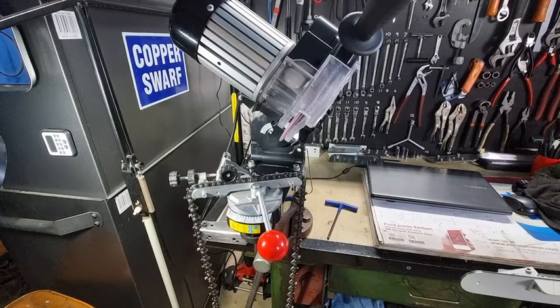If it's very, very light blue and it's only a small amount, you're not going to do damage to the teeth. But if that tooth is very, very blue, there's a good chance that you could damage the leading edge, which is a top plate cutting angle. And that's where you could get some damage because you excessively use the grinder. And that would be detrimental to the hardening of the tooth, and you'll increase the brittleness. You cause all sorts of damage. And that's what you want to avoid. So that's all this video is about, that yes, you can cause damage to the tooth if you do it excessively, overheat it. If you lightly turn it light blue, you will only case harden it by a couple of thou, and it's not going to do any damage to the tooth.